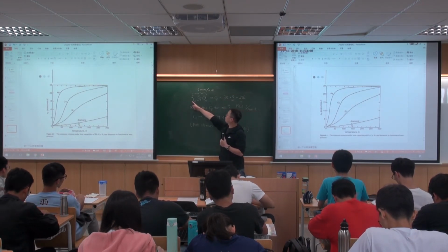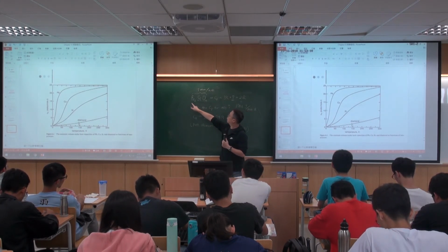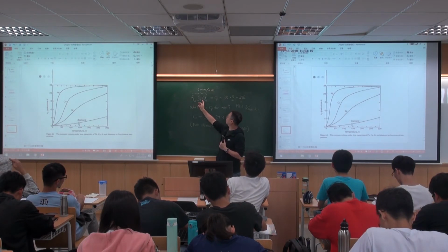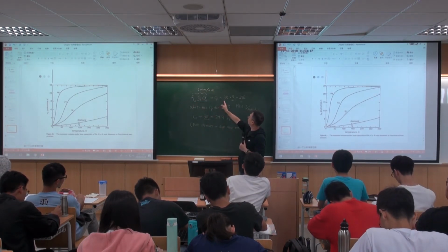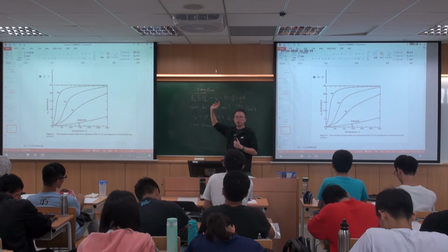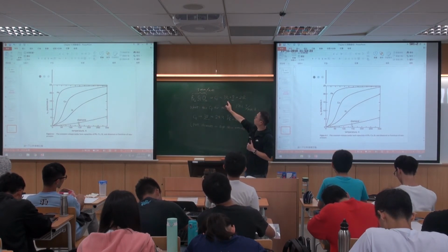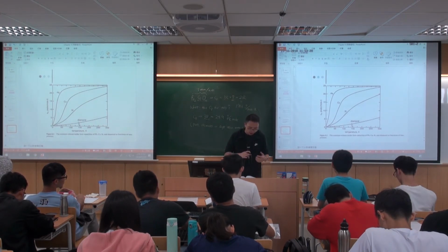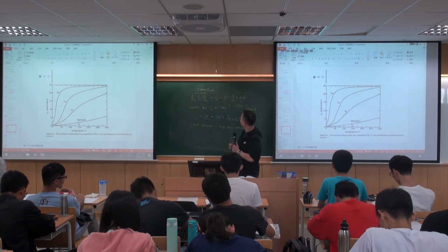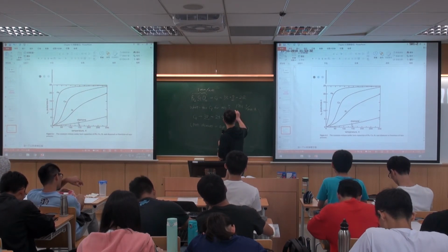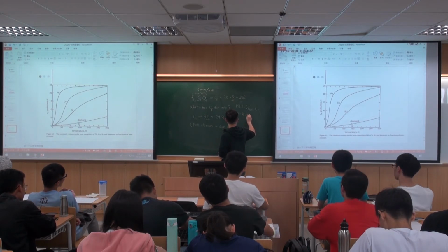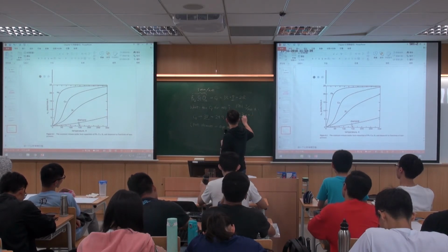So this is the formula unit for this kind of material, iron silicon oxide. And it has 7 atoms per mole, so therefore you have to multiply 3R by 7. So this is an example. In reality, the real experimental value for this one is around 200. So this is a fairly close approximation.